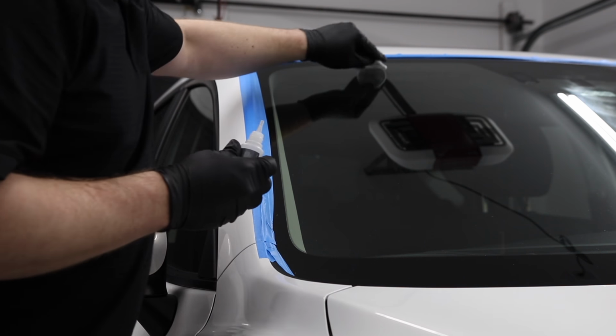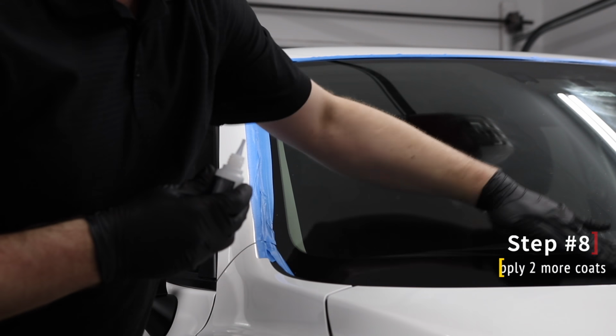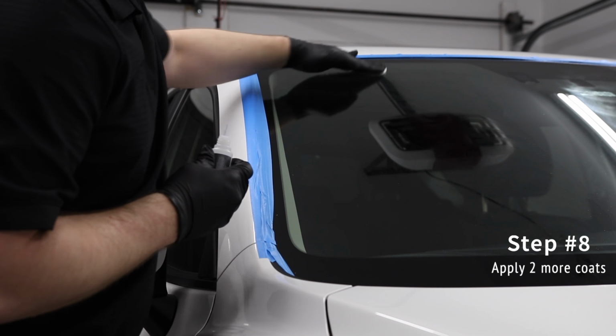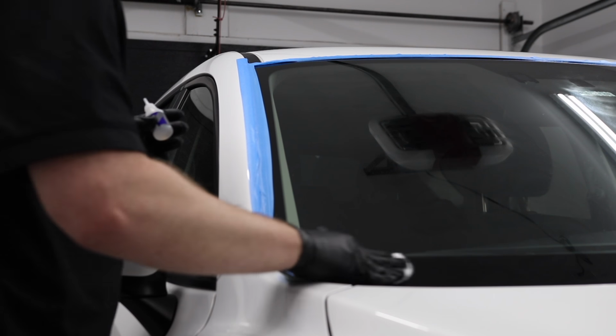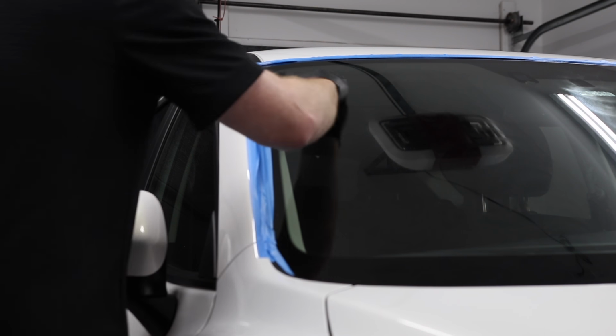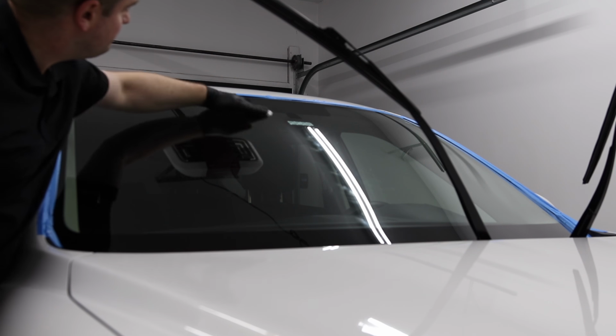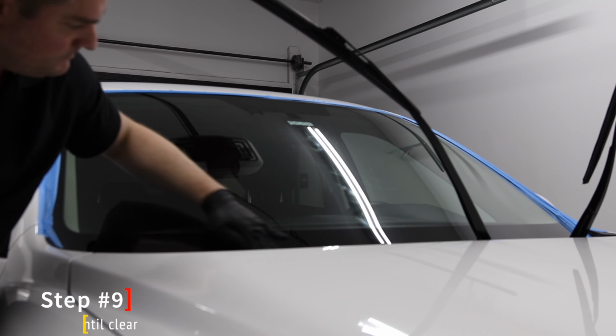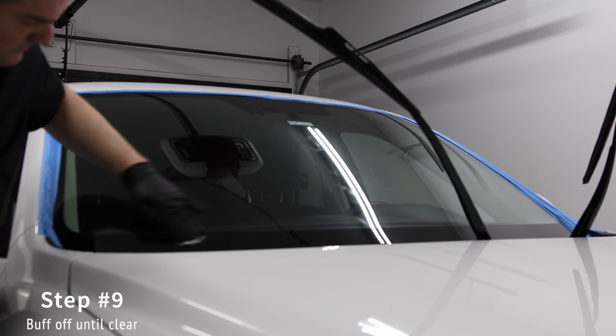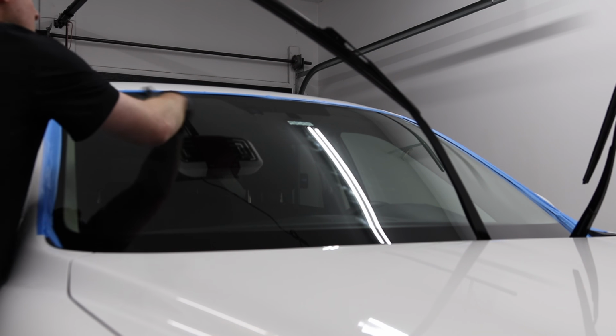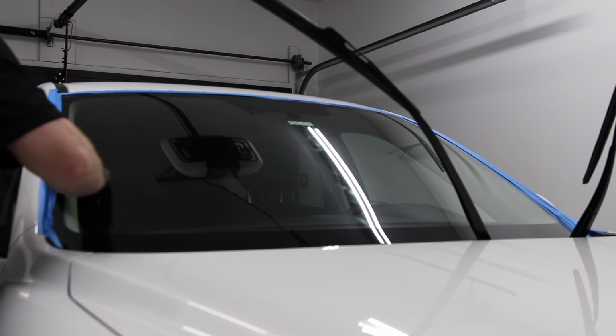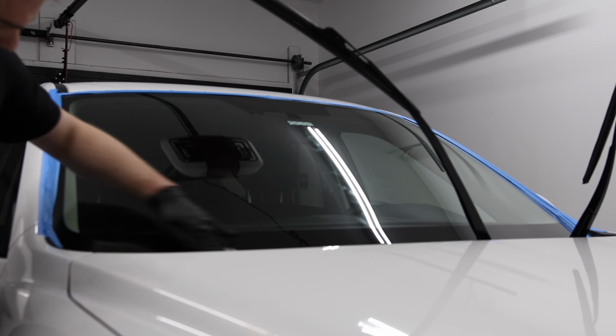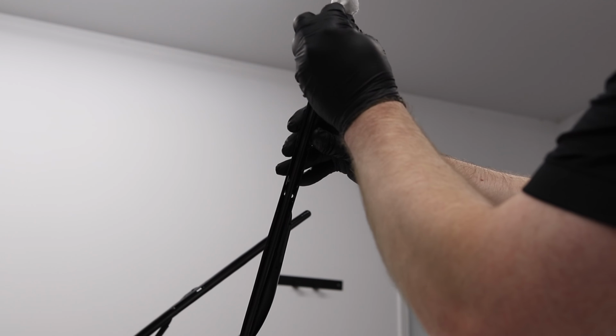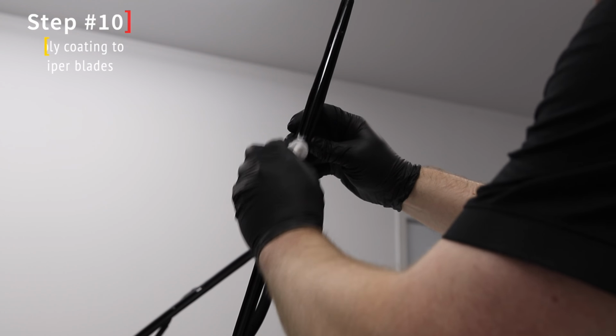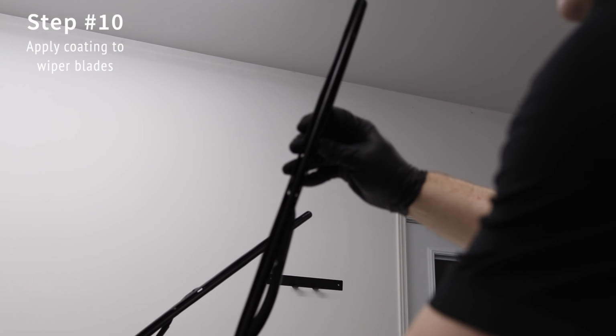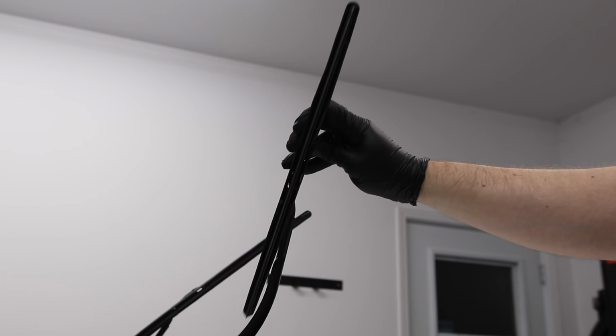Step number 8, on a windshield, repeat steps 6 and 7 two more times for a total of 3 coats. On side windows, only 1 layer is needed. Step number 9, using the same applicator, but with no additional coating on it, repeat step 7, buffing off any trace of residue until the surface is 100% transparent and clear. Step number 10, apply a bit of the coating to the wiper blades and let the blades stand up for roughly 10 minutes for the coating to cure.